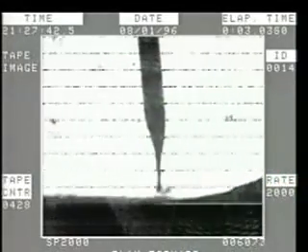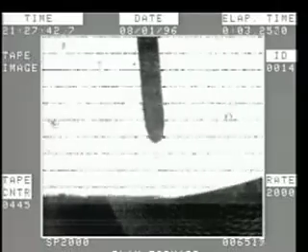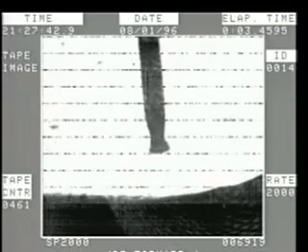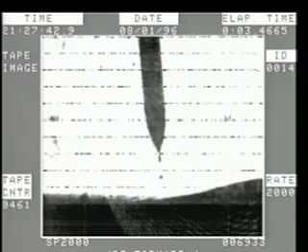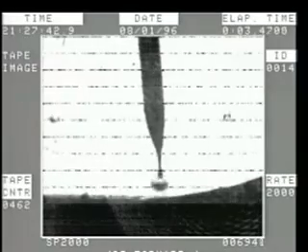The PowerWave power source has waveform control technology. It provides a very fast front edge on the pulse, transferring the droplets quickly. The back edge of the pulse falls at a controlled rate to add the heat input needed to wet the droplet into the puddle. Pulse spray is stable at a wide range of wire feed speeds. The process offers more advantages at both higher and lower wire feed speeds than conventional axial spray. But with the waveform control technology processes, there is much more processing versatility and capability.